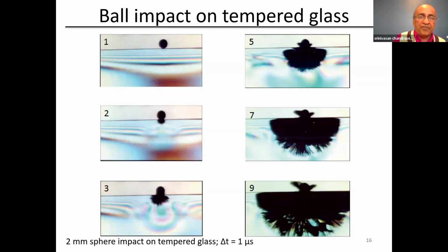If you look at frame 1, there are some fringes. They're not important, but the black fringe tells you, in this case, where the sphere is hitting the block of glass with polarized light shone through it, that the region above consists of material in compression, compressive stress, and below is in tension, pre-stressed. Here again, when the sphere hits the block, cracks are set in motion, the crack propagates, and you see these fingers appear quite prominently. This is a cleaner system.